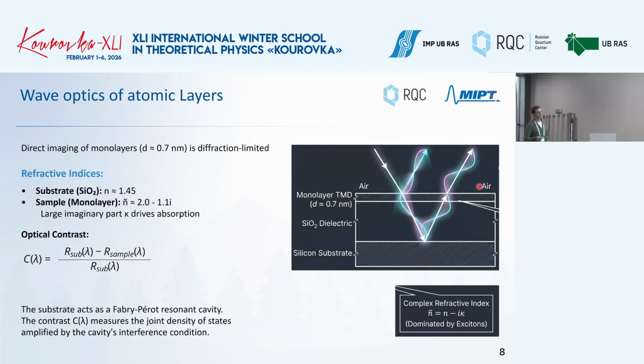Here's the specific, like just the usual experiment. So you have a monolayer. Let's say here it's then transition TMDC, but it doesn't matter. Then you have a substrate, the silicon substrate, and the dielectric between this. So depending on the width, thickness of this dielectric, you have different optical contrast. So it can be described easily.